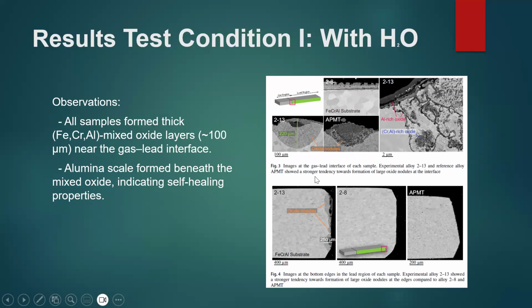We can see in figure 3 the image at the gas interface of the sample. Experimental alloy 2-13 shows a stronger tendency toward formation of oxide nodules at the interface. This is APMT, and this is sample 2-13. We can see the different oxide nodules.